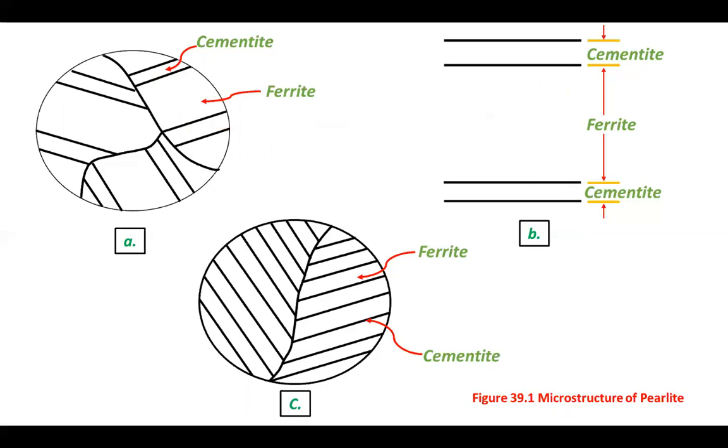But that is the amount ratio. What we see is the volume ratio, but fortunately the densities of these two phases are the same, so the volume ratio is also 8:1. So you see in a pearlitic structure, 8 times the space has been taken up by ferrite, and the remaining space has been taken by cementite, and both appear in the form of lamellae.